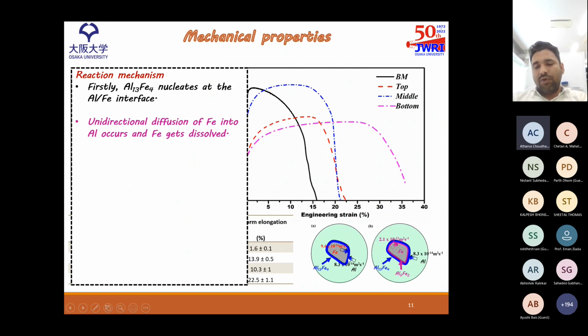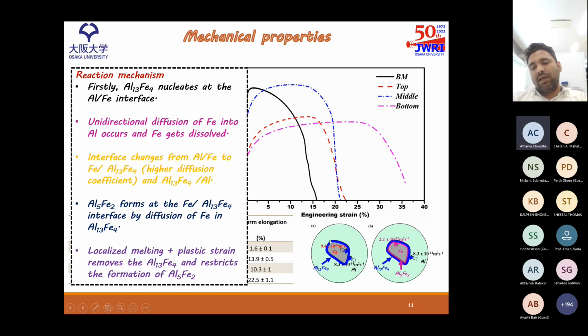So this provides the foundation for the reaction of Al5Fe2. However, in our case, as soon as this layer Al13Fe4 is formed, by the stirring action, it is removed from the Fe particle. And that's why there is no foundation for the formation of Al5Fe2. And thus we have avoided this brittle intermetallic particle from our structure.